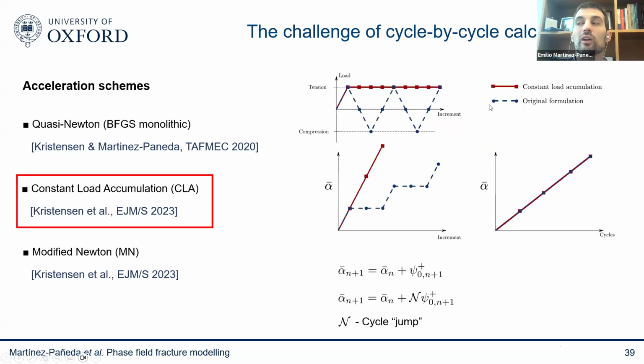We've also proposed a constant load accumulation scheme that is based on the idea that often damage only accumulates during the tensile cycle, so you can jump across these tensile cycles. And we have also combined this with another idea that a lot of people are exploiting that is called the cycle jump. Basically, this idea means that if you are running a simulation to predict a railway component that is going to fail after 30 million cycles, maybe cycle number 26 is not that different from cycle number 27. So instead of simulating every one of those 30 million cycles, maybe you can simulate 1 cycle every 10 and assume that the other 9 are going to be very similar.